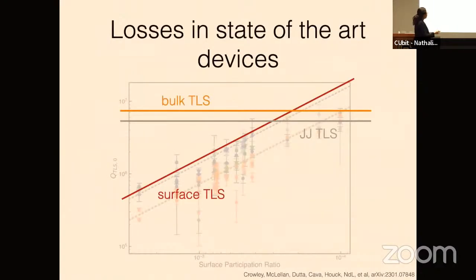Okay, so our current understanding, that probably went by too fast, but the takeaway is that our current understanding of the losses in state-of-the-art devices is that we have this surface TLS that looks like this, a bulk TLS that looks like this, and I didn't show you any data at all, but we also think that our Josephson junctions are now worse than our best resonators. So it is now time to revisit the Josephson junction. And then I'll just mention our packaging loss is way up here. So we have a lot of headroom to continue to improve.